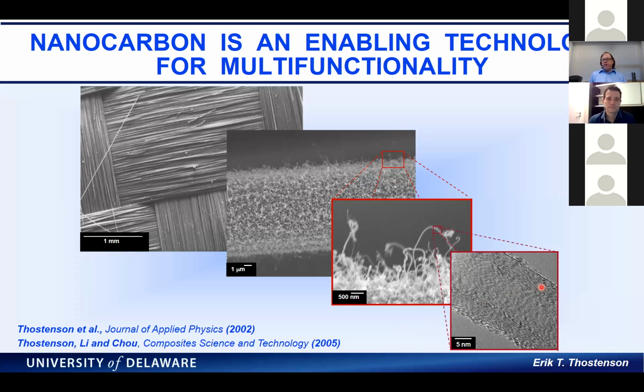Yeah, so we've worked with both. I always consider graphene as kind of a new material we could play with and compare to what we did in carbon nanotubes. One thing is that because graphene is a 2D shape, it's more difficult to get it inside, since you have a long aspect ratio in two dimensions. So as far as getting it into the fiber bundle, you have to really make those sheets smaller. And of course, when you make the sheets smaller, you're reducing the aspect ratio, and you want a good aspect ratio, right? So that's one thing.